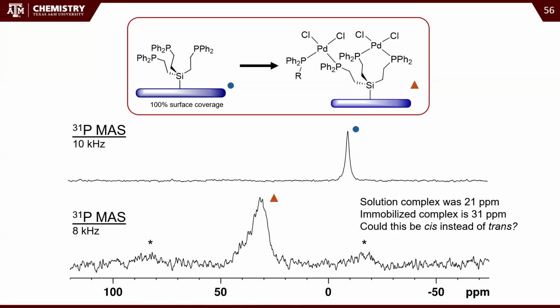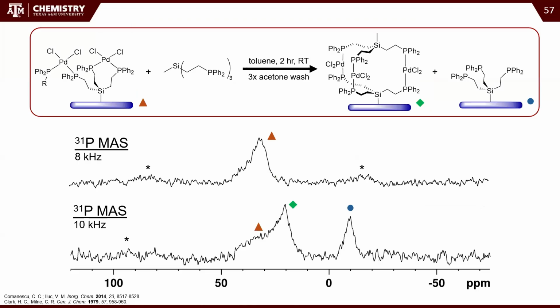on the surface. So I devised this experiment and I checked in the literature, and the literature says, yeah, about 10 ppm. If you have the same complex, you move from cis to trans, it's about a 10 ppm change. And if we make the cis complex on the surface, then we see, yeah, okay, about a 10 ppm change. And we consume a fair bit of that, and we have that signal there. That's the same signal that we see in solution. So it seems like we don't have surface interactions. It's just a difference of cis to trans shift.